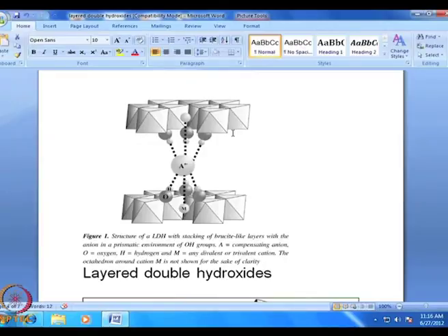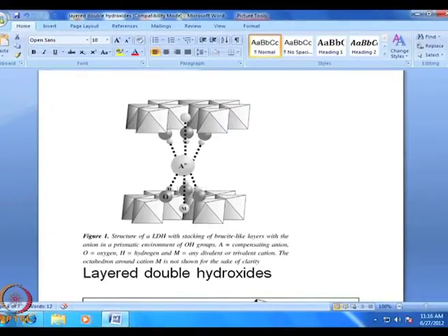The anion here is not exfoliating the clays, it is not forcing the clay particles, but rather they are taking the magnesia octahedra, the brucite layers, and stacking them at heights as per the size of this anion. If I require small distances, the anion shall be a much smaller one, whereas if you want to put in large distances, the anion shall be of the appropriate particular size.